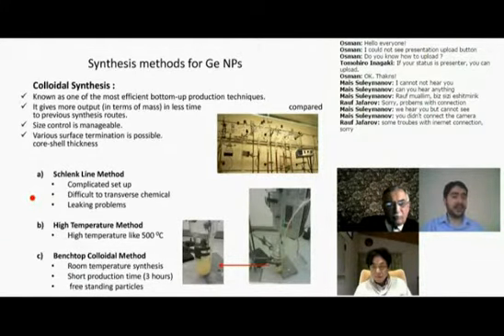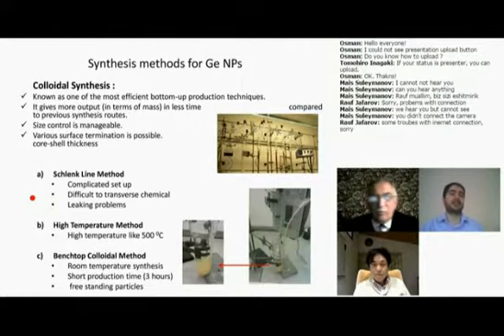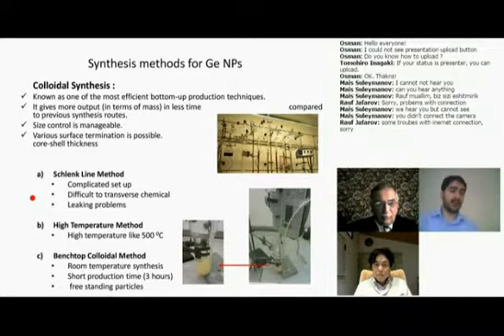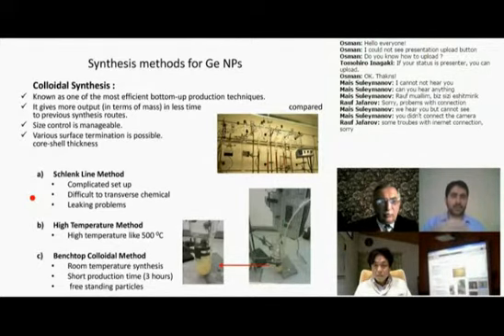What we are using in our lab is a very easy and facile method, colloidal synthesis. In colloidal synthesis, size control is important. We can control size precisely, and various surface terminations are also possible over the core of the germanium nanoparticles. It also has different variants, like the Schlenk method, the high temperature method, and the benchtop method. These two, as you can see in this picture, require a very complicated setup. It's difficult. For example, if there is a leak, it's difficult to find, and transferring the chemicals is also difficult. The high temperature method is also expensive.